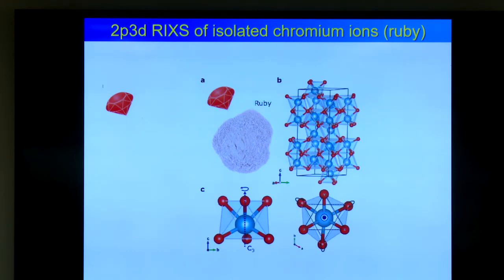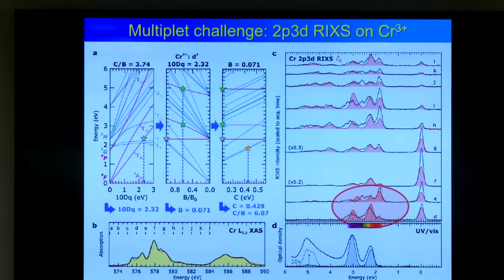This is something I like to show because it is a nice example. One study we did was on ruby. And from our point of view, that was not because it's a nice color, but because it's a very simple system. It's a chromium impurity in alumina, so you can approximate it almost perfectly as a single chromium atom in an innocent oxygen host. And then we did the RIXS experiments. And then I want to show some analysis of the RIXS. So this is the X-ray absorption, chromium L edge, and you cannot see the difference between theory and experiment.